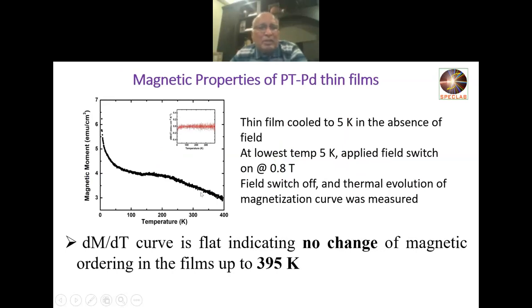Here we are showing the magnetic data over the temperature region, which is done with the lowest temperature. We put the field at something like 0.8 and then remove the field. Then we just follow the temperature path, the thermal evolution of the magnetization, and take the dM/dT. You can see it is completely flat. There is no change in magnetic ordering in this material in this region, because that shows that the magnetic phase transition is above room temperature.